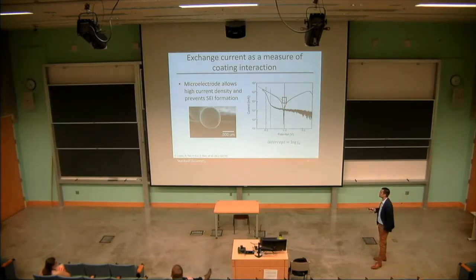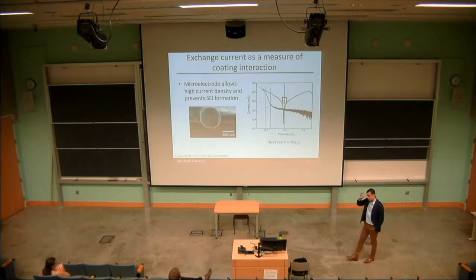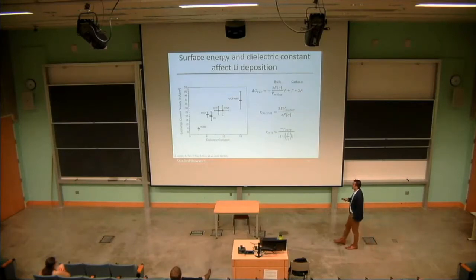So this is a 25 micron tungsten microelectrode that we scan at 200 millivolts per second. So this whole CV here is acquired in about 4 seconds, which is very fast and almost as good as we can do to prevent any SEI formation and really probe the pure interaction between the polymer coating and the lithium surface.